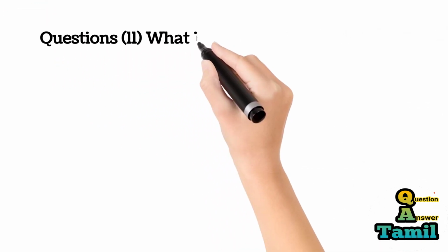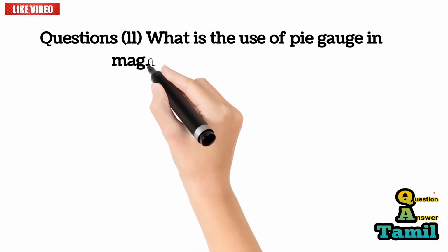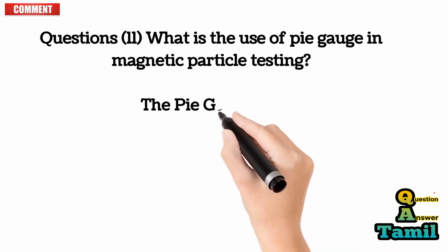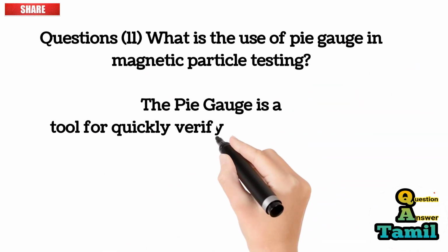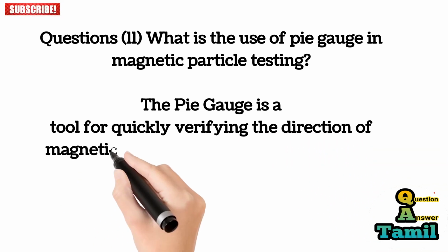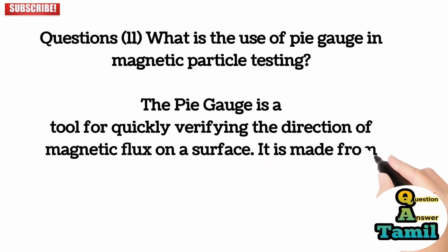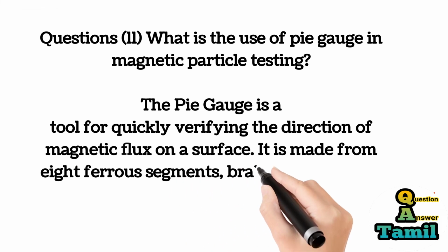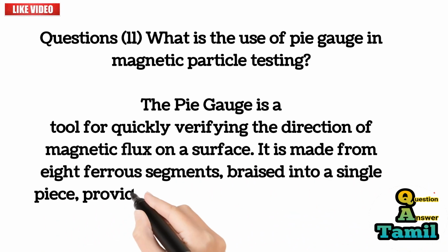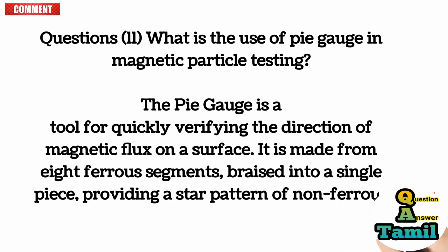Question 11. What is the use of pie gauge in magnetic particle testing? The pie gauge is a tool for quickly verifying the direction of magnetic flux on a surface. It is made from 8 ferrous segments, brazed into a single piece, providing a star pattern of non-ferrous discontinuities.